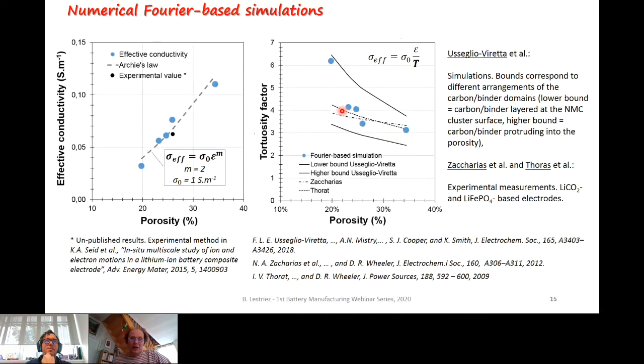Maybe, and also for the denser electrode, our result is closer to the higher bound, maybe because in our case we have NMC clusters and small NMC particles that in some way are also protruding into the porosity. And our results are also compared with experimental values from Zacharias and Thorat that were obtained for LiCoO2 and LiFePO4 based electrodes. Their measurements were for electrodes that were 30% porous and more. So we have extrapolated their trends, but we have an acceptable, good agreement. So we are fairly confident, happy with our simulations.